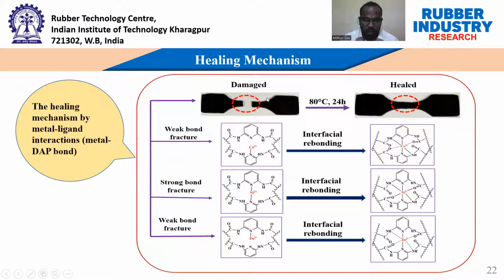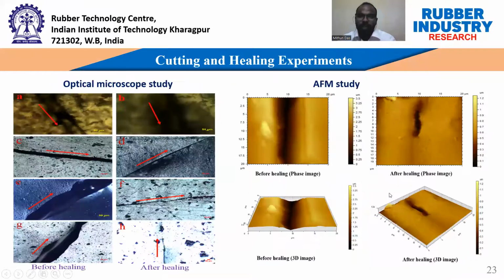So what happens when we cut the sample is that the dynamic metal coordination bonds separate from each other. At 80 degrees centigrade after 24 hours, these dynamic metal coordination bonds are rejoined and then heal the sample. And whether the sample was healed or not is understood by the optical microscope study and the AFM study.